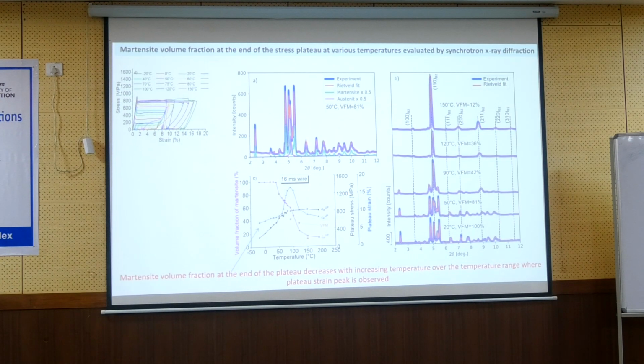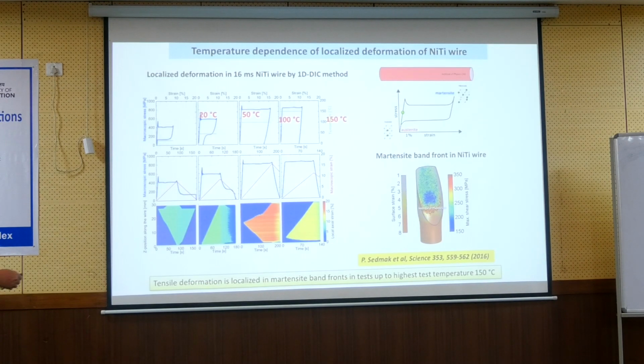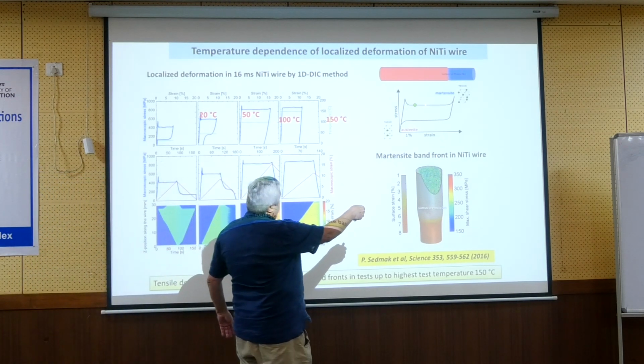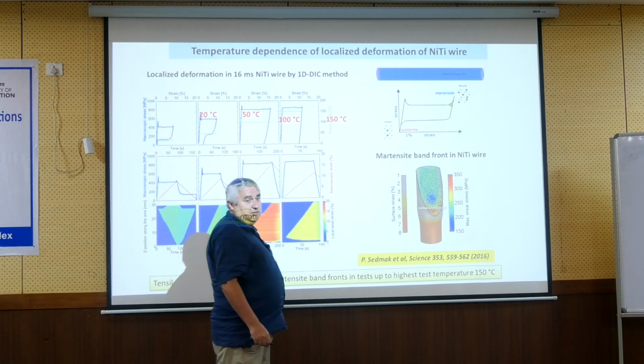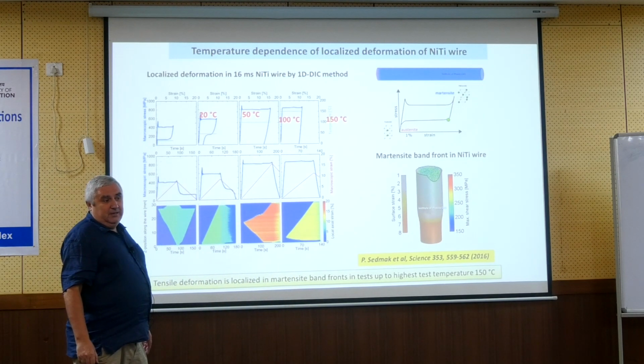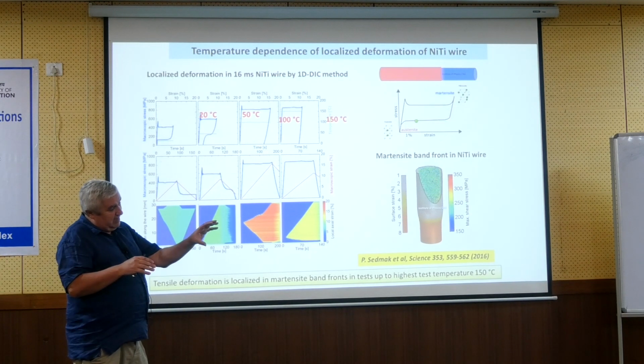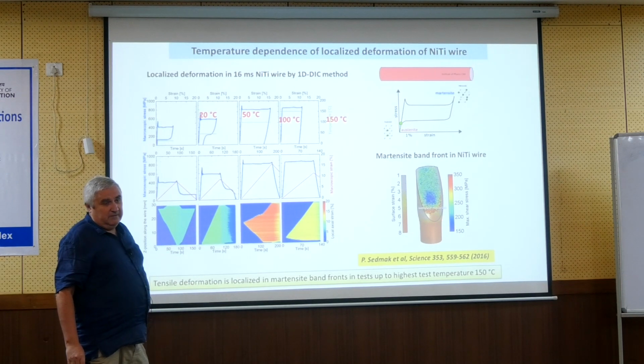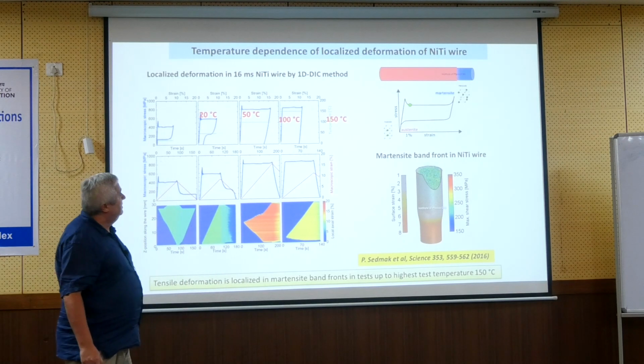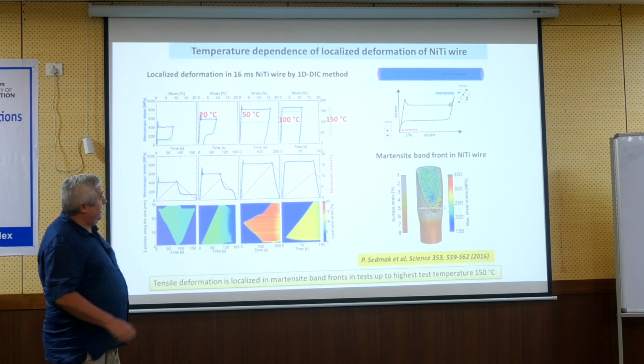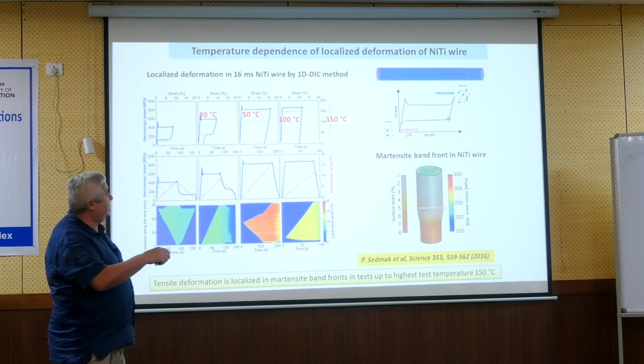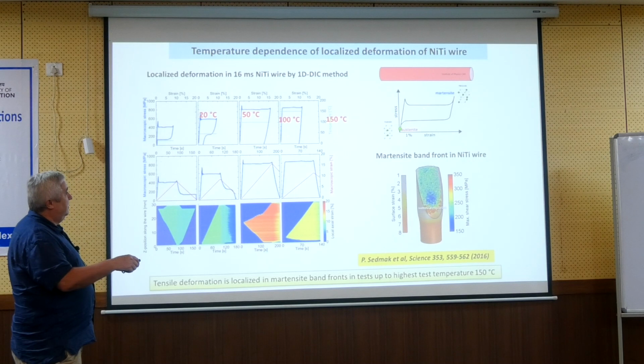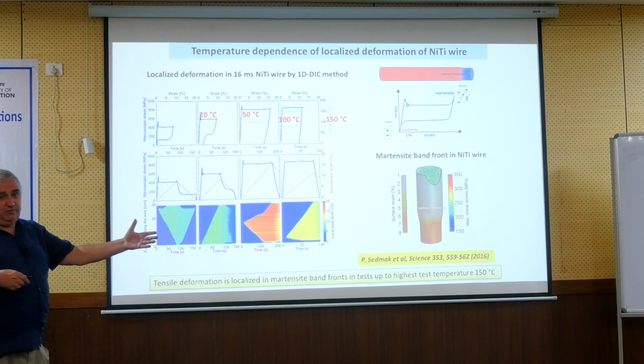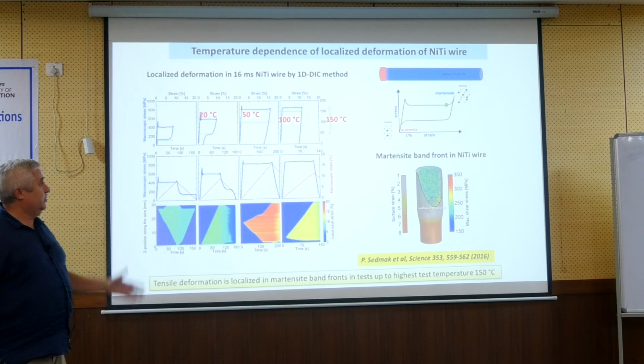When we stretch a nitinol wire, let's say to 4% or something, within the plateau region, and we stop there and unload it from that point, you have half of the wire in martensite and half of the wire in austenite. When we unload it, the half which is in martensite will go back to austenite, but the other half will be intact. In that experiment, is there no heat treatment? Every nitinol wire behaves like this, almost every one. This is just a schematic picture, but approximately the heat treatment could be any of the heat treatments which we use, which give rise to superelasticity. So it would look like that.